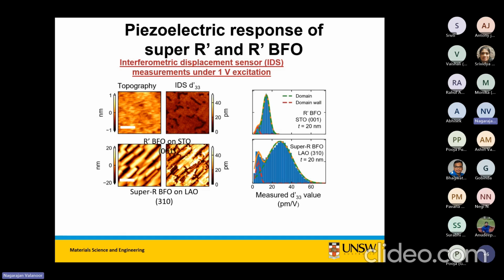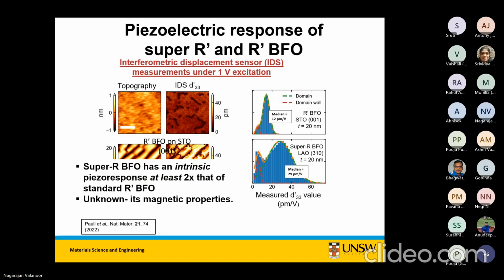We find that our film, so you got to remember our films are still under clamped constraint. So our RBFO itself is showing around 12 picometers per volt, and the super RBFO is about 3 times larger. Okay. So we are very confident that this is a new, quite elastic form of bismuth ferrite, which has got very exciting piezoelectric properties, and we will do a lot more work on this in the coming years.